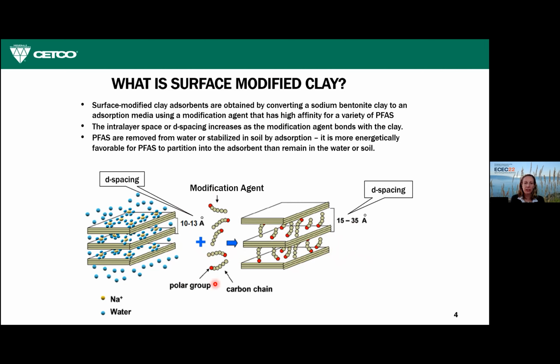The modification agent is specific for PFAS in that it has a positively charged head group that will attract the negatively charged head groups of negatively charged PFAS, which most of those that are of regulatory concern are. And then it has a hydrophobic hydrocarbon chain that is a driving force for adsorption for the perfluorinated chain of PFAS compounds. So it has a dual driving force in terms of adsorption of PFAS, and it's more energetically favorable for the PFAS to partition into the adsorbent and associate with the surface modification than it is to stay in the water.